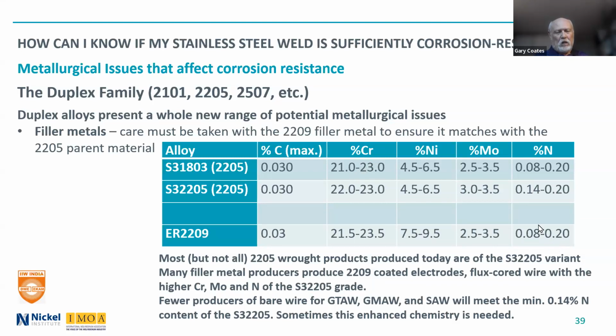And this can create a problem if you're welding the S32205 alloy if you haven't checked to make sure that the filler metal you're using does have a higher chromium and molybdenum and especially nitrogen content. Now, you'll see, first of all, that the filler metals are all elevated in nickel, and that is also because nickel is easy to add and will help in that transformation. And so it works in many cases, but not all cases.